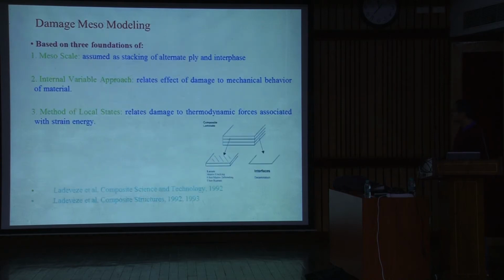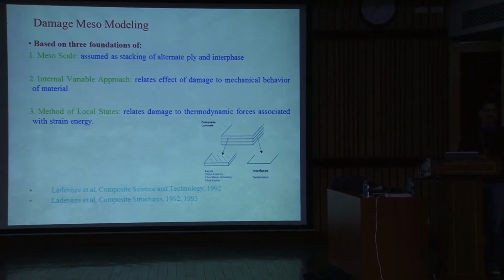The first assumption that is made is the mesoscale. It means you are assuming the laminate as an alternate stacking of layer and interface. Layer means you have the matrix and the fiber, and the interface is pure matrix material. It is a very thin layer made up of matrix material. So you are talking about these scales. This is the ply, which is of thickness 0.15 or 0.125 millimeter, that is about 125 microns. This is the scale you are talking about.